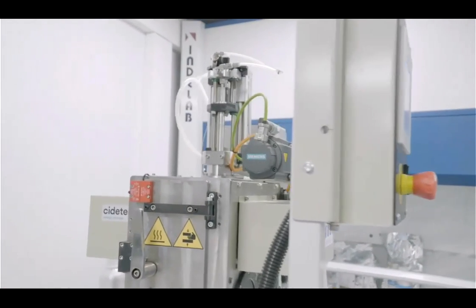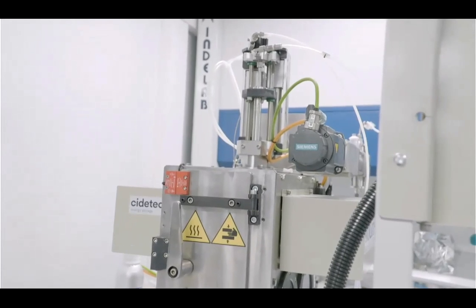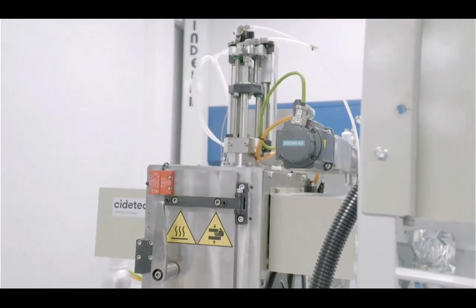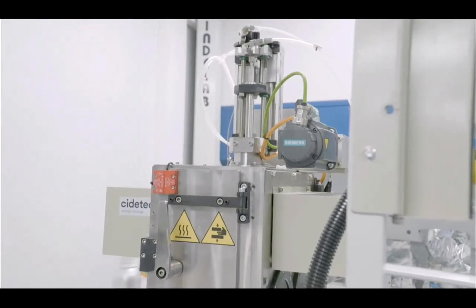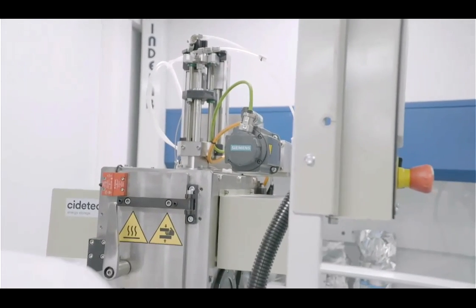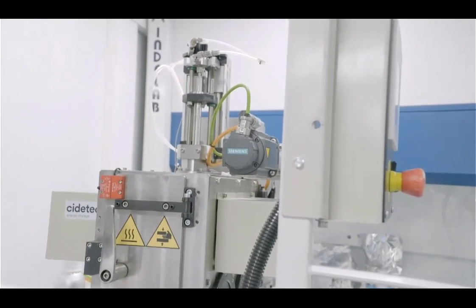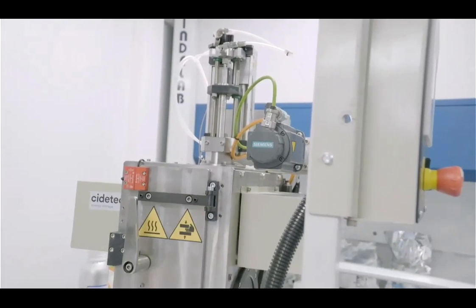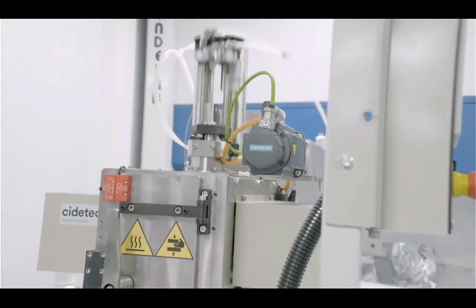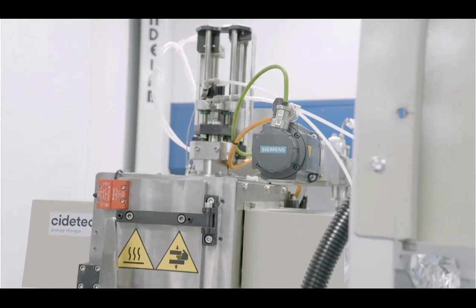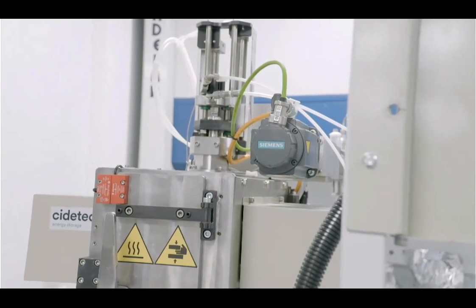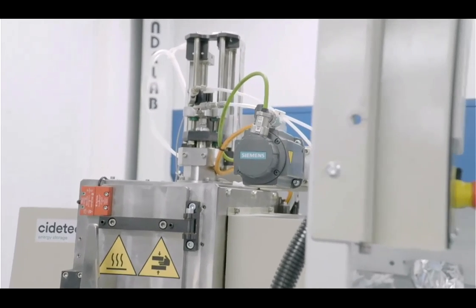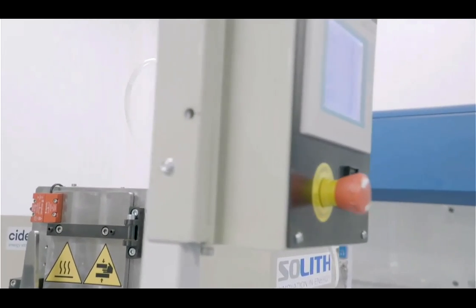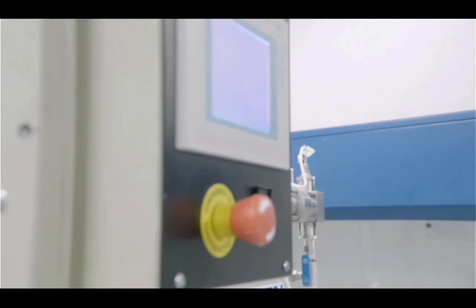So when we have added the electrolyte, the next step is the wetting of the electrolyte. So how do we do that? We apply what we call a massage to the cell. Okay, so we apply a pressure profile to the cell. So we generate some vacuum, we break the vacuum, we generate the vacuum, we break it, and we activate the capillary effect, and the electrodes will be wet little by little.